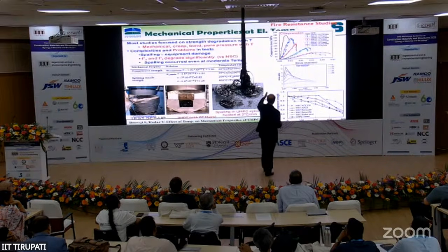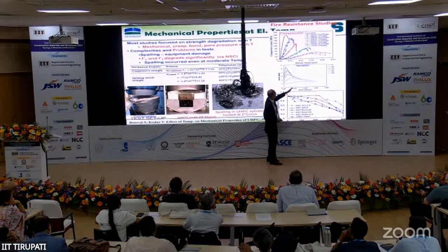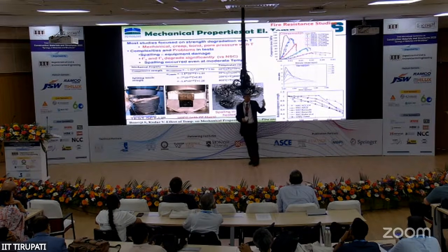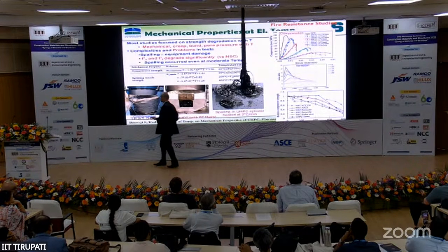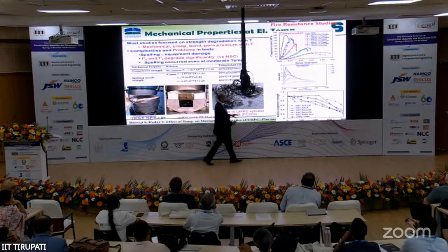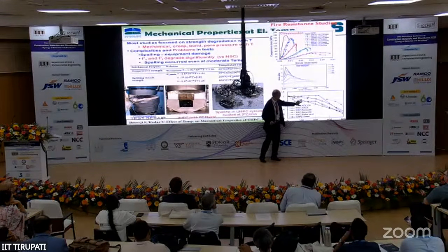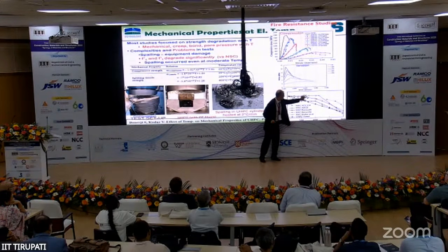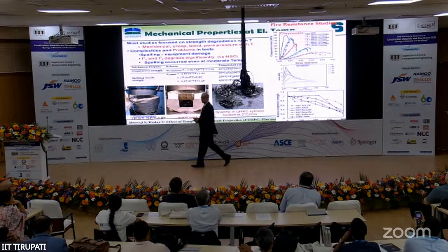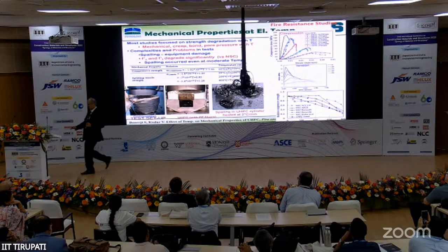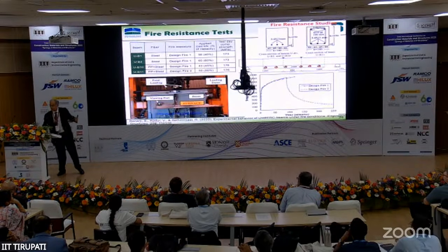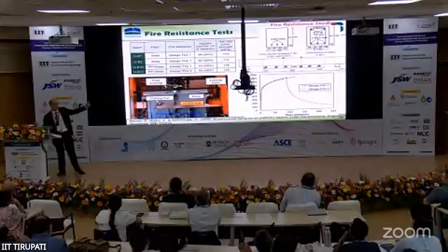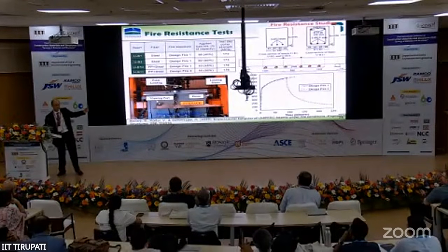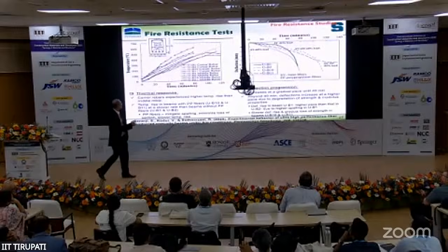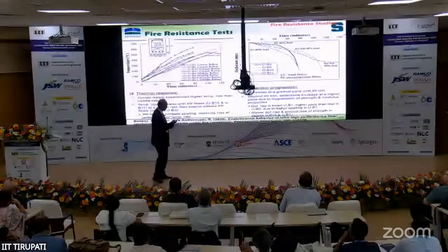So this is tensile strength as a function of temperature similarly. So we established, and that's the comparison for normal strength concrete, high strength concrete, and UHPC here, high strength here, normal strength here. Okay, so these relations are very important. We followed it with a number of tests again for structural members, columns, beams, and all this. I'm going to just show you when these columns were made, the temperatures.